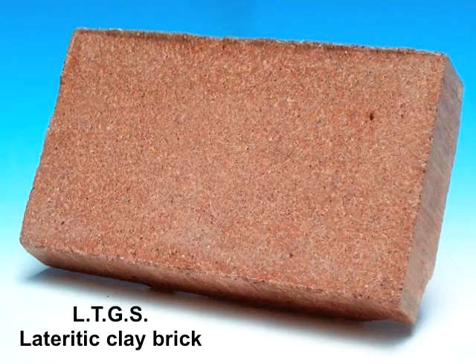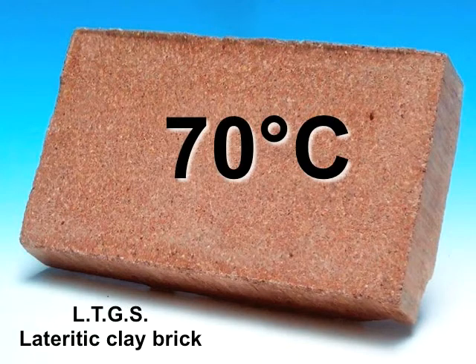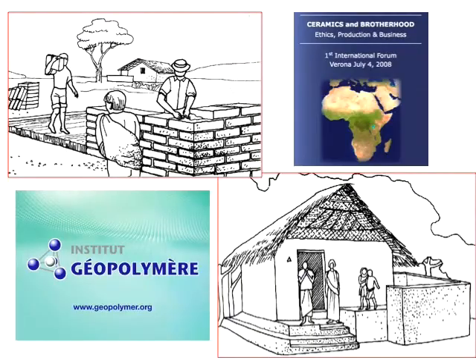And then we can make bricks. Bricks not at 700, not at 800, not at 1000 degrees C, but at 70 degrees C. Totally different. This is chemistry. It is not the firing of the elements. And this is our program for the Ceramic Brotherhood, and that will be fostered now.